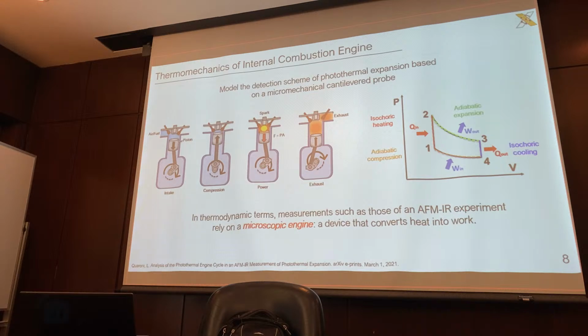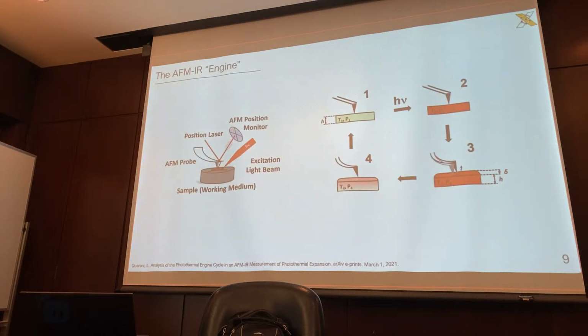So this paper that I found states in thermodynamic terms that the measurements, as in an AFMIR experiment, rely on a microscopic engine. I thought this was an interesting thought experiment. So what they term as an engine is, if we look at the process between 1 and 2, we have a minimum volume, as shown here. As we introduce our light to the system, we see rapid thermal excitation in the process of 2. Moving from 2 to 3, we actually see this thermal expansion occur, and this is where we reach peak volume. From process 3 to 4, we see a loss of temperature and then a decrease in volume back to the first position there.